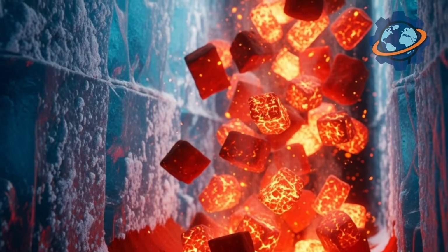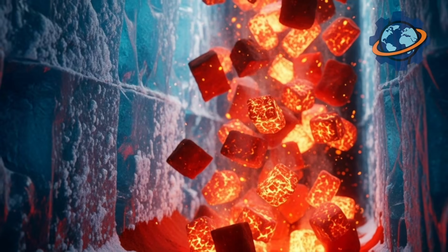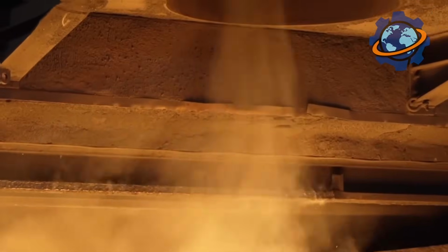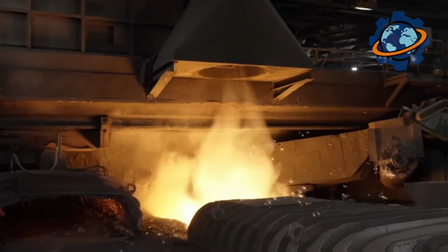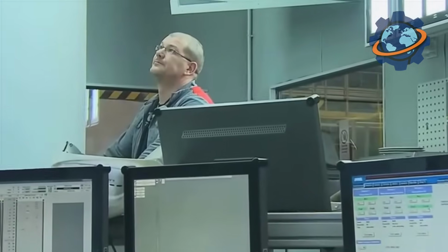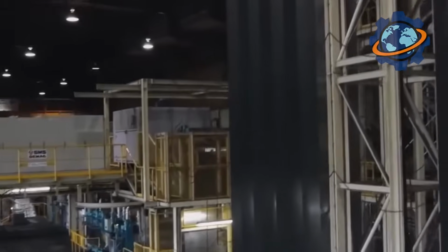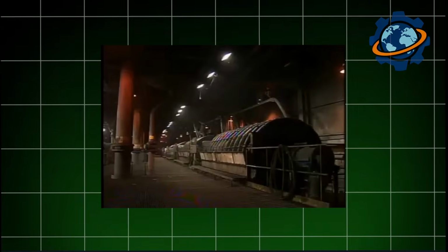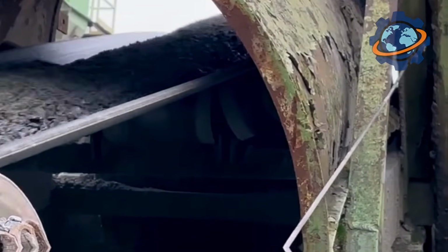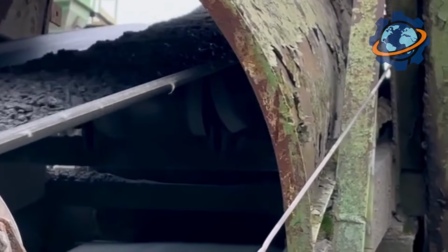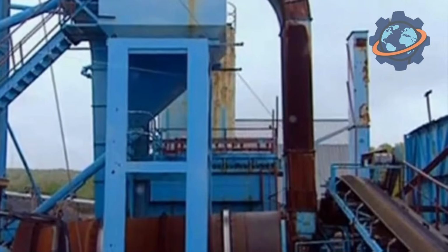Liquid nitrogen instantly strips heat from the rubber. You hear a distinctive sound, not the roar of a shredder, but a light, brittle crackling. This is thermal shock. At this temperature, a phase transition occurs. The rubber passes through its glass transition point. The rubber can no longer stretch. It can no longer cushion impacts. It becomes glass. At the exit of the nitrogen tunnel, these glassy chunks face a high-speed hammer mill.